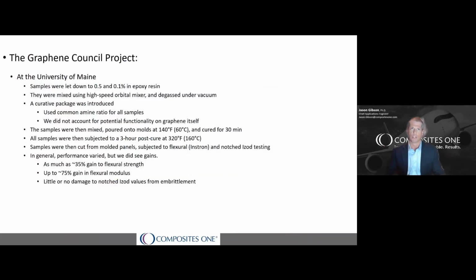So let's jump into those results. As Paul mentioned earlier, we had 17 sample materials shipped to the University of Maine for testing. These samples were anonymized and no one, including myself, knew whose material we were testing, giving an unbiased, objective testing protocol. We took the 17 master batch samples and blended them down to 0.1% and 0.5% loading of graphene by weight into the bis-F epoxy.